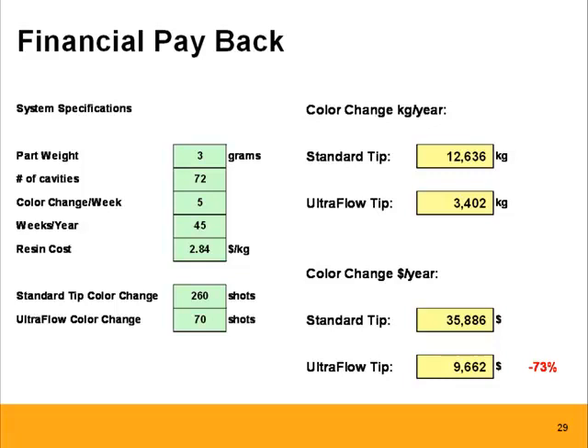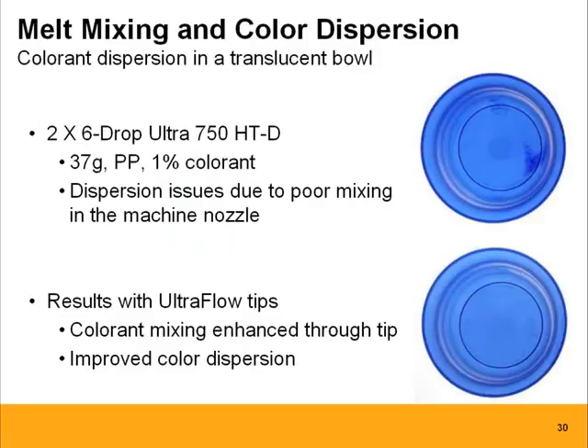Another topic that I would like to talk about briefly is melt mixing and color dispersion. I think it's very important from a screw and barrel point of view, because otherwise you start wasting colorant. In this case, because the melt wasn't properly mixed, you can see in this area of the part we have color concentration. Remember from the beginning I said, especially if you work with the smaller particles, with the organics, more likely to happen in that respect. And often processes overcompensate for this by adding more colorant, which is of course a more expensive way of doing it.